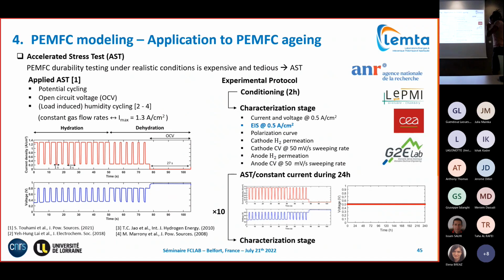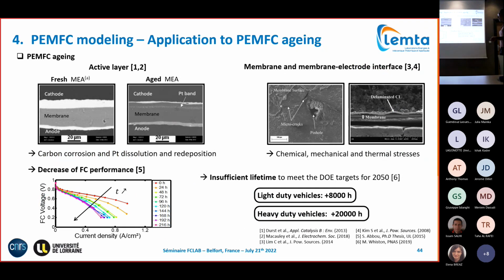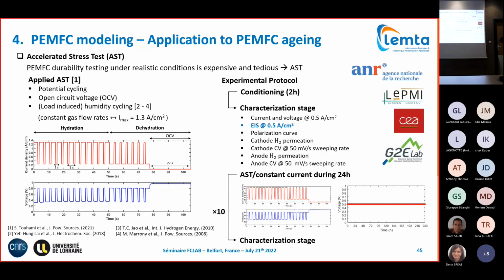Okay, so we also do some research in order to identify different physical phenomena that are at the origin of aging of the electrodes and the membrane. Measuring the evolution of performance during normal operation would be very expensive in time. Therefore, a convenient way to analyze aging is to use accelerated stress tests, which means you reproduce the stresses encountered during operation in a very accelerated procedure.